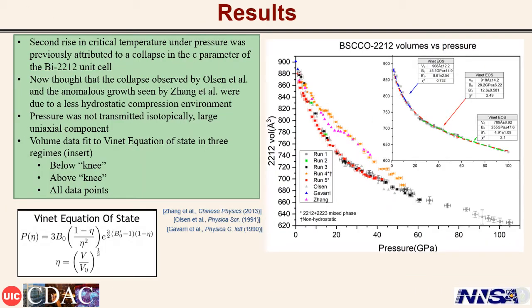Previous compression experiments by Olsen et al. up to around 60 gigapascals observed a planar collapse in the 2-layer BSCCO variant. This collapse occurs in the same pressure regime as the second rise in Tc as seen in transport data. Additionally, anomalous growth in the A parameter was seen in compression experiments by Zhang et al. It should be noted that all other experiments were performed using a methanol-ethanol mixture as a pressure transmitting medium.